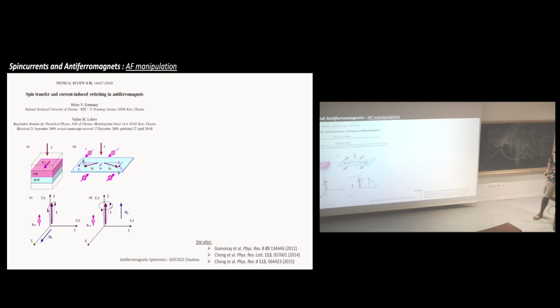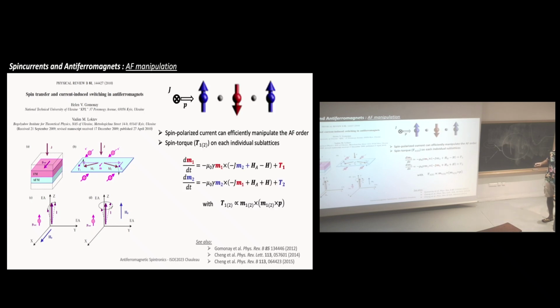But of course, there is also the question: can we manipulate the antiferromagnetic order using spin current, which is basically the counterpart of it. And there have been some proposals that it should work a bit differently, but it should work the same way. Basically, when you have a spin current entering an antiferromagnet, then you will have a torque, called spin torque, equivalent to what's happening in ferromagnetic material, but it will act on the antiferromagnetic layer in two opposite ways. Okay? And the way to understand that, it has just an opposite action on the two sublattices, which creates an opposite effective torque, typically. So this is exactly what's happening.